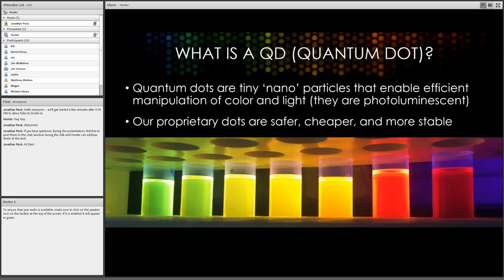For those of you who don't know what a quantum dot is, I thought I'd just dedicate a slide or two to that. These are really tiny particles of semiconductor that are effective at manipulating color and light. In other words, they're photoluminescent. They can absorb one color and then convert that to a new color. And why are they called quantum dots is because of a quantum effect of having a band gap that's changed with the size of the particles. So we can make this rainbow of colors like you see in these vials with the exact same compound. This happens to be copper indium sulfide. But just by changing the size of the particle, we change the band gap, and so we change the color of light that they absorb and emit.